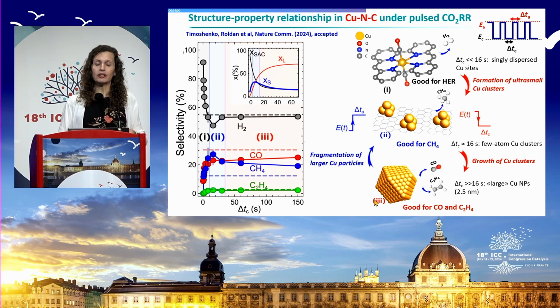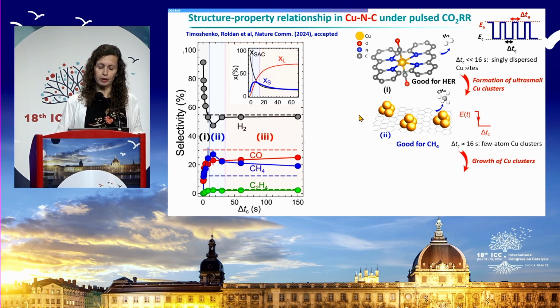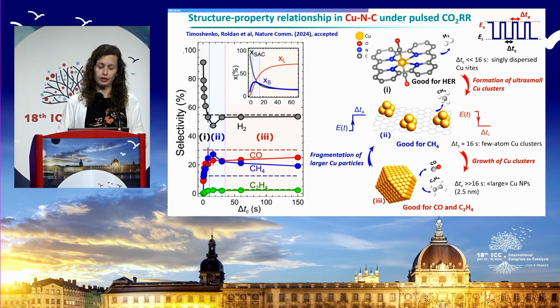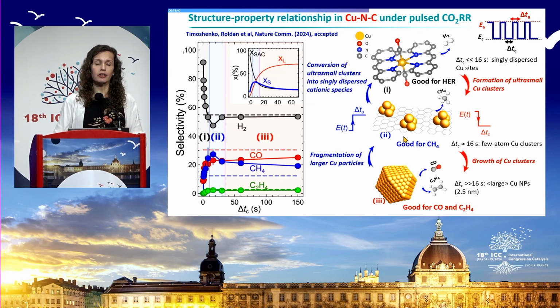So imagine I'm in the electrolyte. I have my nanoparticles, and my clusters are going to be oxidized and also hydroxylated. And so this is easier to redisperse when we go into these conditions. And this is what we are doing here. I'm changing the length of the anodic pulse, and I can redisperse and go back to this structure. And this is highly reversible, and we don't see a lot of material loss. You have some copper going into the solution and then being redeposited.